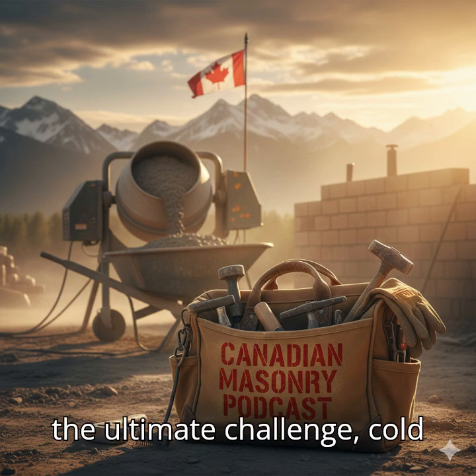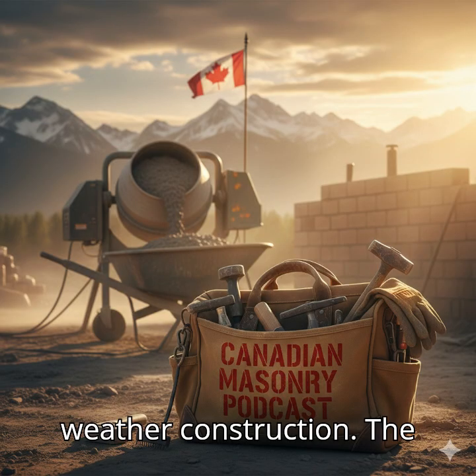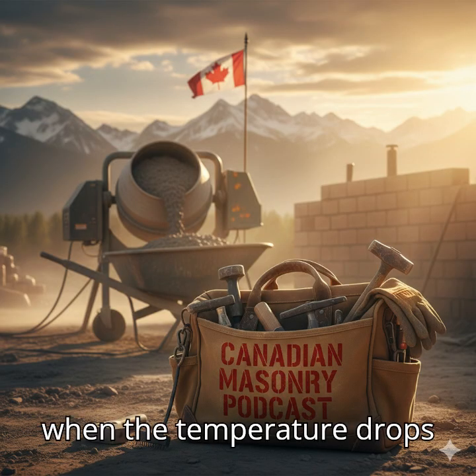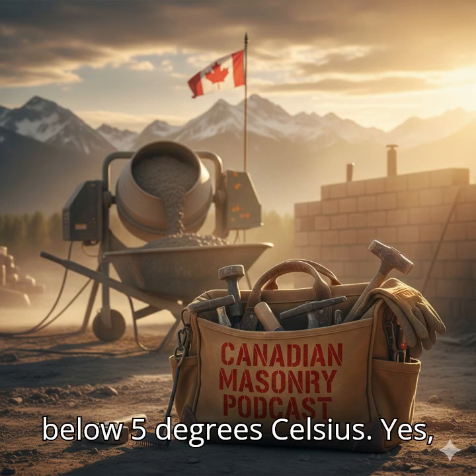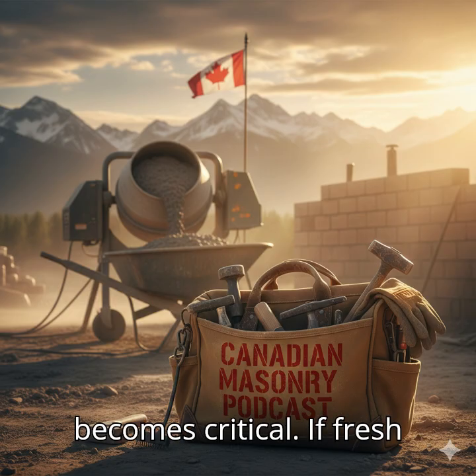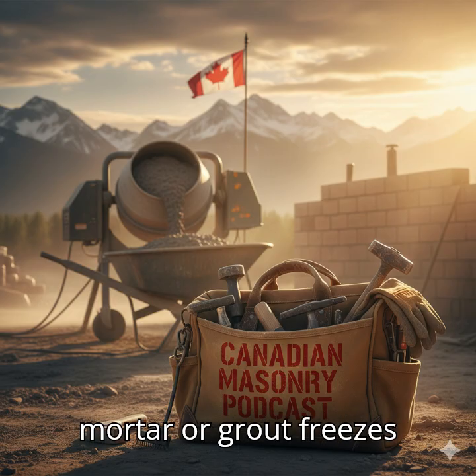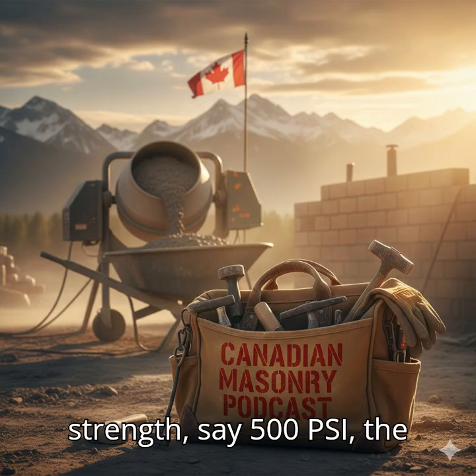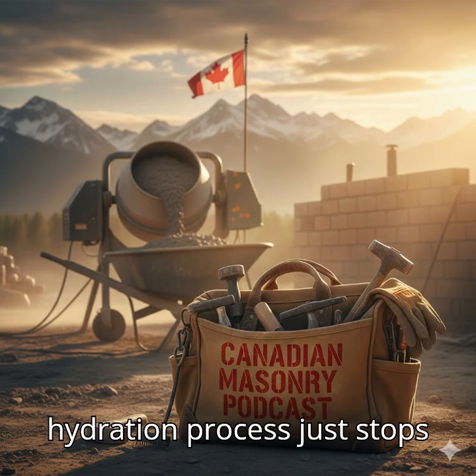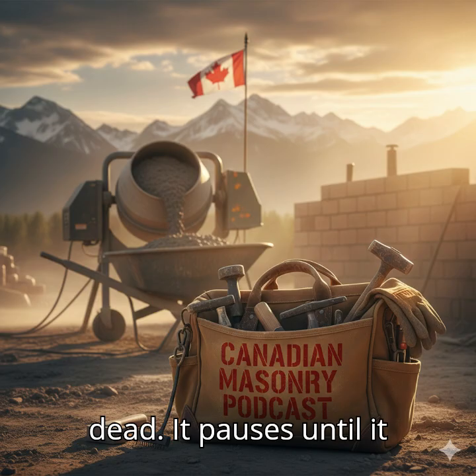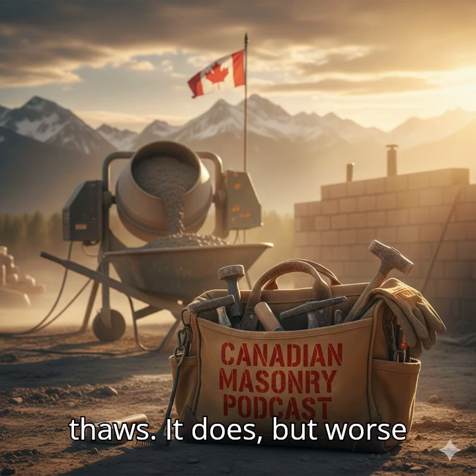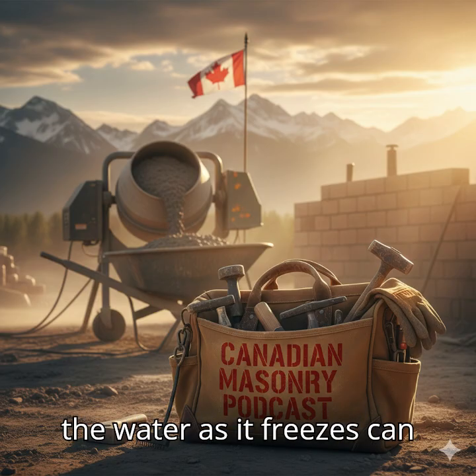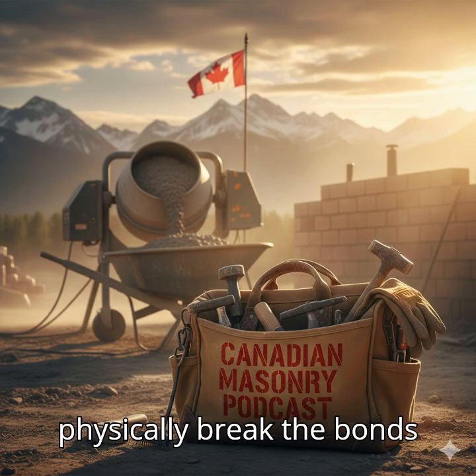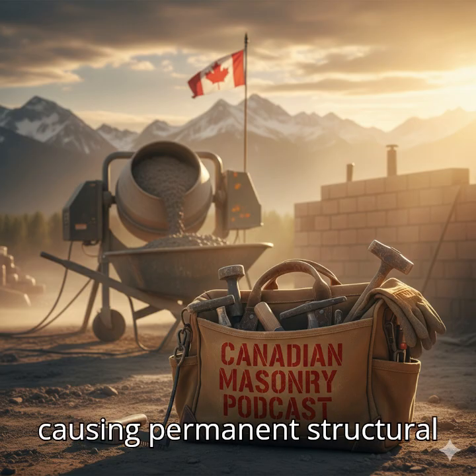Now for the ultimate challenge, cold weather construction. The standard gets very strict when the temperature drops below 5 degrees Celsius. Yes, because the freeze risk becomes critical. If fresh mortar or grout freezes before it gains enough strength, say 500 psi, the hydration process just stops dead. It pauses until it thaws. It does, but worse than that, the expansion of the water as it freezes can physically break the bonds that have already formed, causing permanent structural damage.